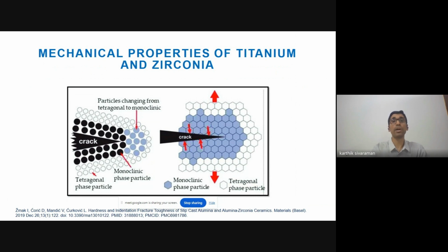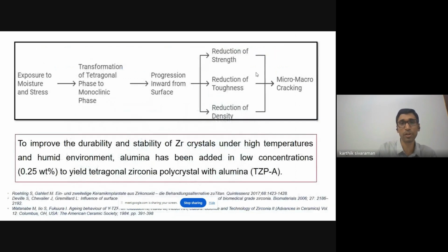To avoid that, a series of stabilizing oxides were added, the most common of which is yttrium oxide. That resulted in a martensitic-like transformation toughening of the material, and is the main reason why the mechanical properties of zirconia are improved compared to its predecessor, alumina. However, we also need to understand that under certain manufacturing conditions, especially under exposure to moisture and stress, there is a transformation of the tetragonal phase to the monoclinic phase from outside to inside.